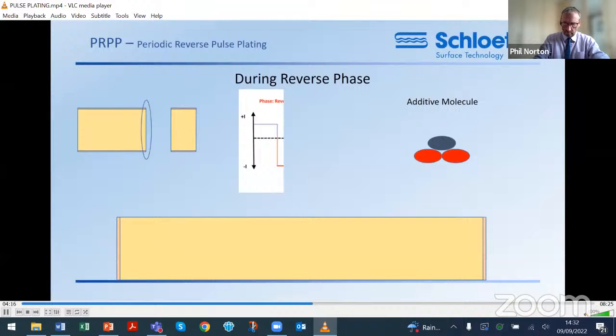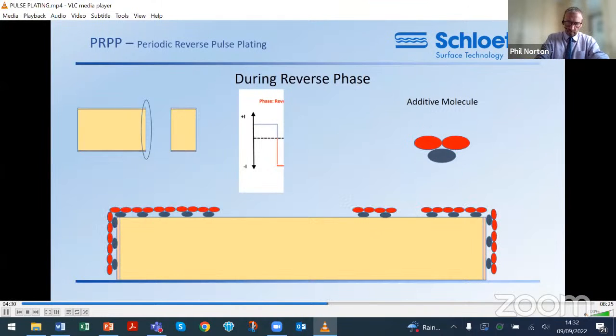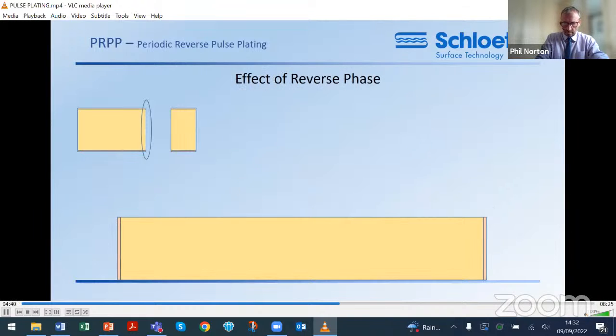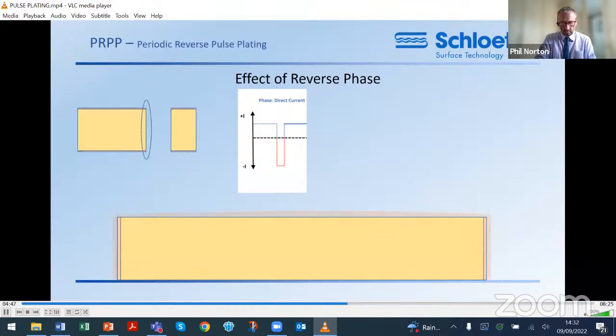During the reverse phase of pulse plating, when the current is moving in the opposite direction, the reversal has the same effect on the additive molecules, which flip over. In high current density areas, for example on isolated features or on the knee of a hole, layers of molecules can build up on top of each other. When the current reverts back to the DC phase, it takes a little time for the molecules to reorientate themselves, and the plating in high current density areas is actually inhibited, as shown here in this exaggerated example. So the full effect of the reverse phase can be to plate more copper in the hole than on the surface. This sequence of events is also referred to as polarization.